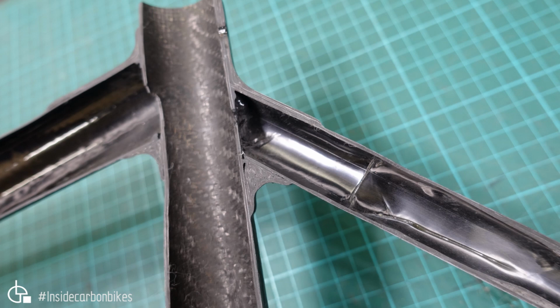And the other angle, so you can see where it's bladder molded, a little bit of bladder wrinkling through here, with an extra bit of resin ridges and stuff. Not really a big deal. You can see through here and through there where there's just a bit less compaction like we saw on the other one. Porosity in this region through that lug as well, but that's pretty minor. So yeah, again, very similar to the other one.